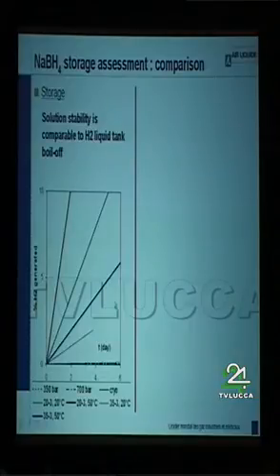So it is important to have this evolution of the decomposition of sodium borohydride. This is NaBH4 lower concentrated solution, and of course the decomposition is enhanced. We compare that to the boil-off of a cryogenic liquid hydrogen tank, and it is the black line here. So the conclusion is that the solution stability is comparable to liquid hydrogen tank boil-off. So the solution cannot be stable with time.